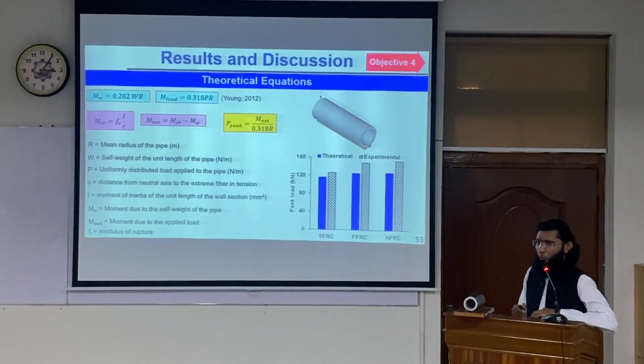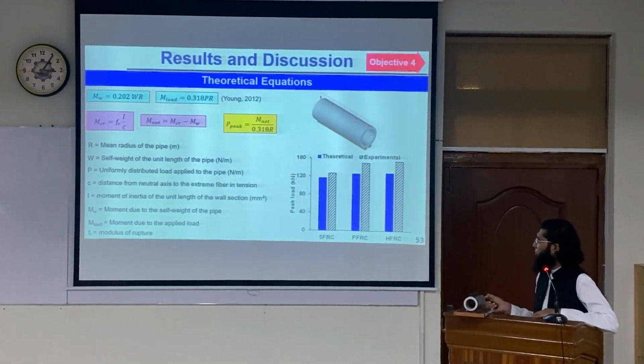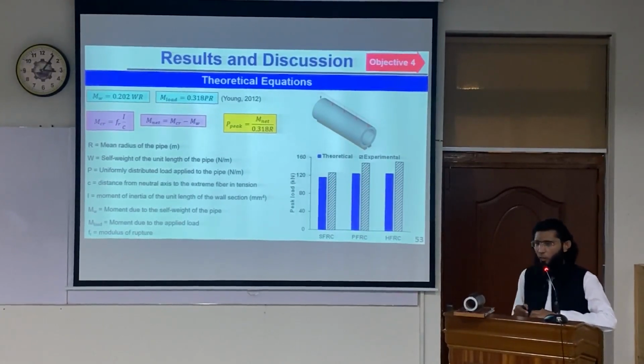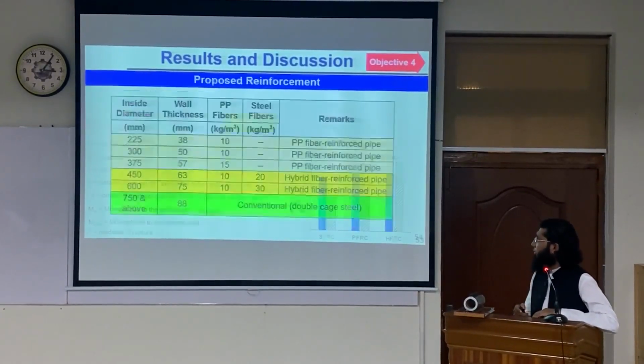Even further computational work was done based on the recommendations of the external examiners. Theoretical equations were also developed in order to predict the capacities of these pipes. The theoretical equations could give an estimate which was slightly on the conservative side as compared to the experimental results, which means they could be used for design purposes.